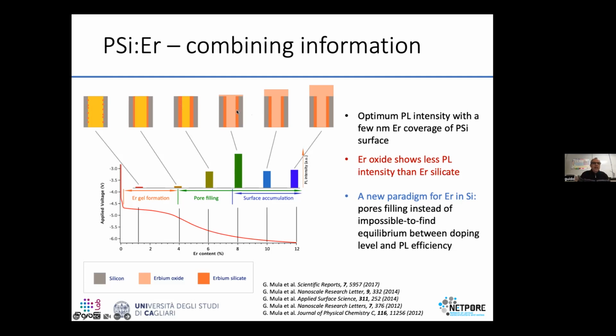And you have your maximum when you have the pore completely filled with the two components. In the clear here is the erbium oxide, and this is the erbium silicate, which is a tiny layer covering the porous surface. When you increase and you have your erbium oxide on top, then your luminescence decreases. And this shows that your optimum is when you have the two compounds present, so the silicate and the oxide. What is interesting here is that in this region, where your previous maximum was indicated, so 1–2%, you do not have a significant luminescence. But if you go to this situation when you have the pores which are filled and just a tiny covering layer of erbium oxide, at this moment you have the optimal intensity.